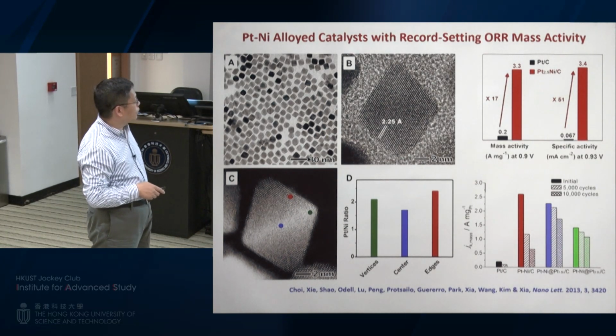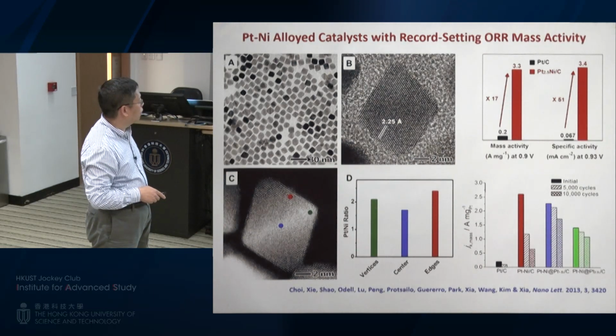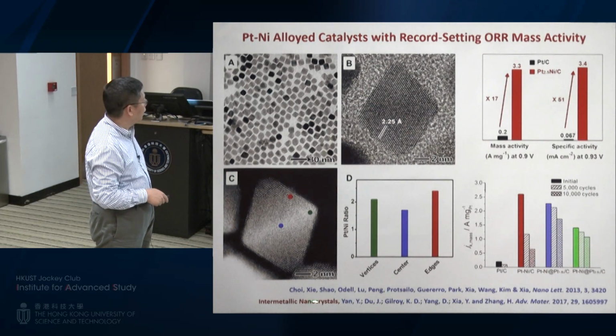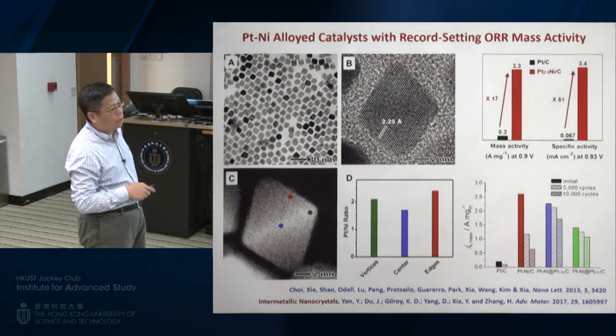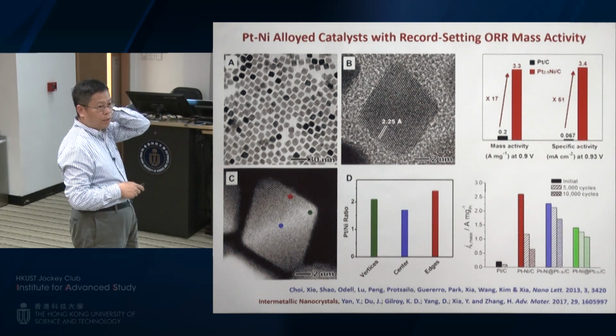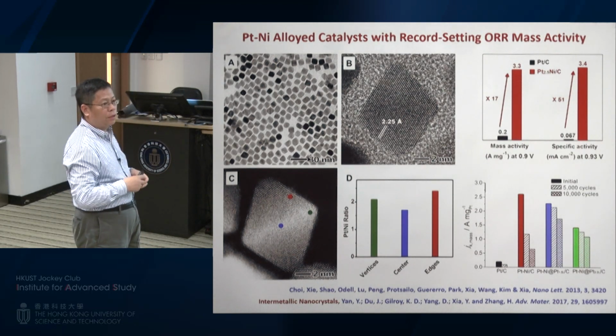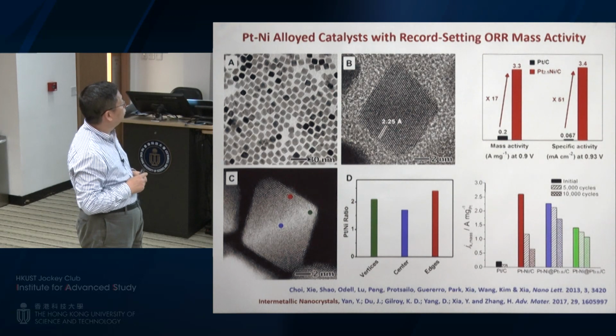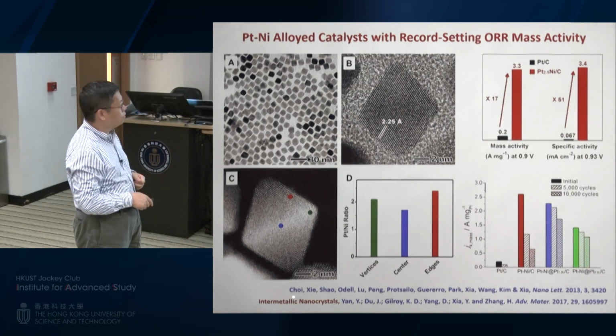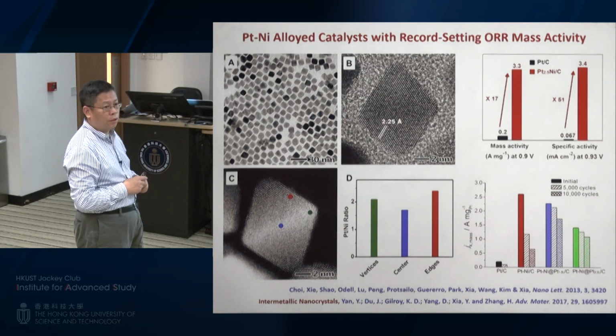So there are two options to make them stable. One of them is based on intermetallic nanocrystals. Alloys tend to be less robust because the nickel could be easily leached out. If you make intermetallics, that system should be more stable.